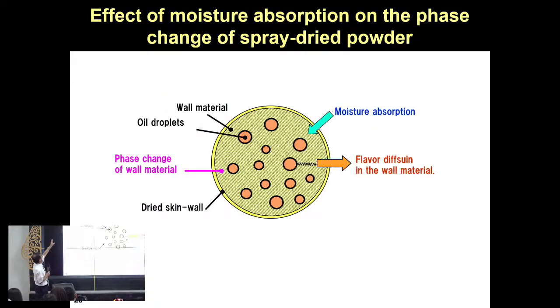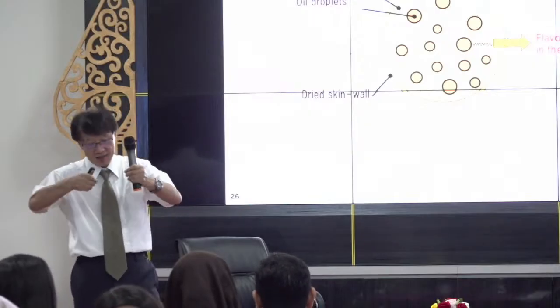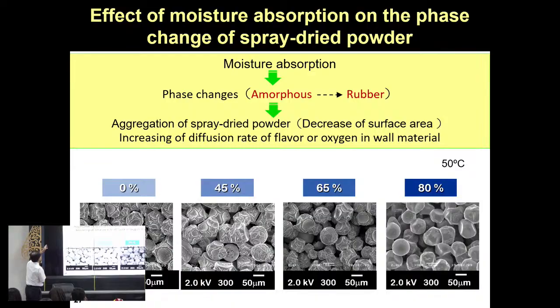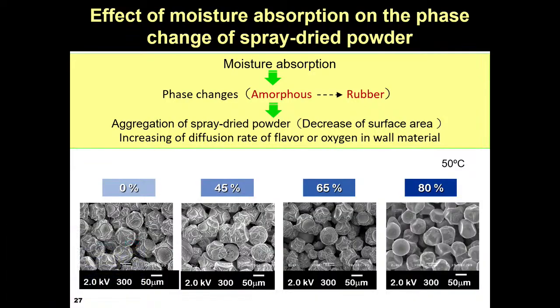So, the effect of moisture. The candy absorbs the water, and the candy becomes soft. And also some kind of cookie, a hard cookie: the cookie absorbs water, moisture, and becomes soft. This behavior is important, the effect of moisture absorption on the phase change of spray dried powder. Here the environment humidity is 0%, 45%, 65%, 80%. Some powders absorb moisture, and the powder structure changes.